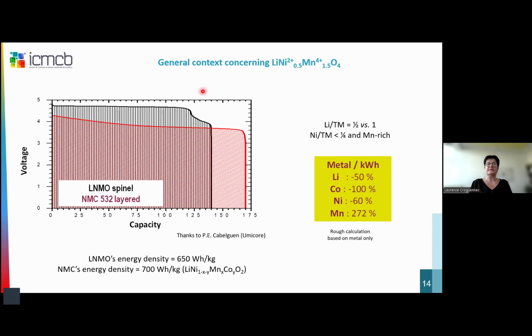And you can see first that if we compare here the electrochemical curve of these materials here in black versus a conventional NMC here in red, we can see that with these LNMO materials, considering the energy density, we can really compete. We have, considering the materials, 650 watt-hours per kilo versus 700 for the NMC chemistry. But I would say the great interest for these materials is really the fact that it's a manganese-rich material, and it's also a lithium-poor material.